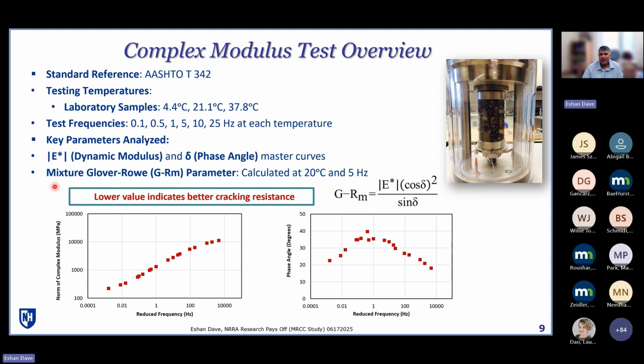From cracking perspective, there's one parameter that has been often explored. That's a rheological parameter. Now, oftentimes you hear this in context of binders called Glover-Rowe parameter. There's also an equivalent of it on the mix side called Glover-Rowe mix parameter. So we were able to calculate this parameter using the complex modulus test results, and I'll show you those. In general, this parameter indicates how stiff is your mix, as in how much stress it will generate when loaded, and also how quickly it can shed its stresses through creeping or relaxation processes. And so typically we want a lower value for this parameter in order to have a better cracking resistance. So when you have a lower value for this parameter, usually that means that that mix would have a better cracking resistance.